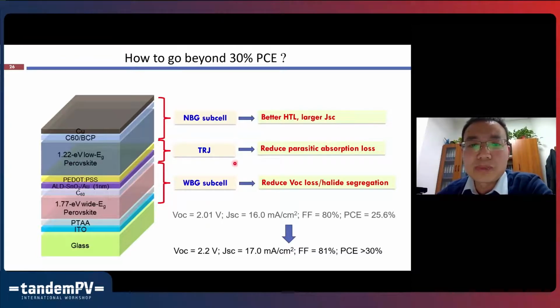And also for the tunnel recombination junction, if we can further replace the PEDOT layer, we will be able to reduce the parasitic absorption losses, and this will give us a chance to increase the short circuit current density. And also, if we can further improve the quality of the narrow bandgap perovskite itself, we will also have a chance to increase the short circuit current density further and also the fill factor. So I think going beyond 30% is quite reasonable. It might be achievable in the next 2 or 3 years.